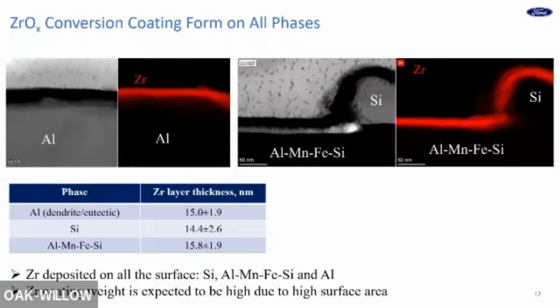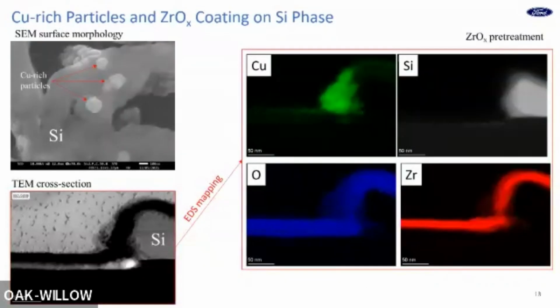So zirconium pretreatment has been well studied on aluminum alloy, like body sheet or extrusion. So we know what happened on pure aluminum, what happened on the manganese silicon iron particles, but there's very limited information about its formation mechanism on the silicon, because based on the current understanding of the zirconium formation mechanism, it seems it shouldn't form a very thick or uniform zirconium pretreatment on the surface. So to have a better understanding of what happened on the silicon phase, how the zirconium forms on the silicon, we did a further analysis on the deposition on silicon.